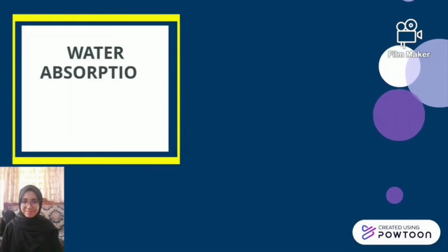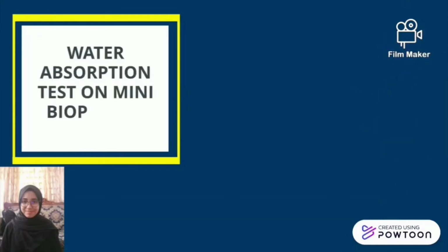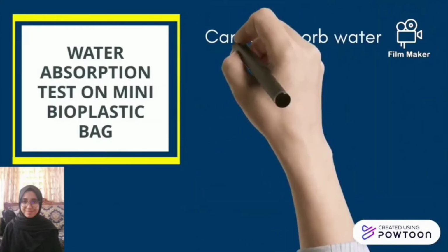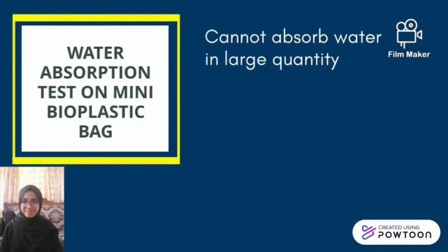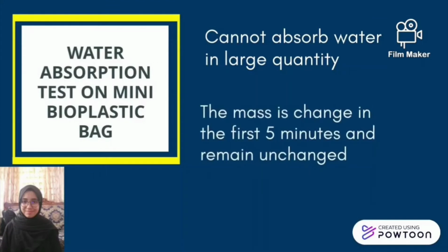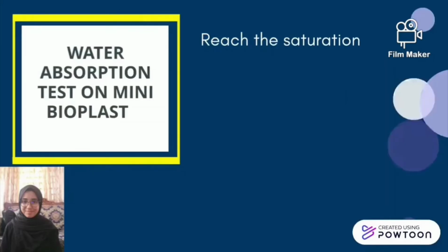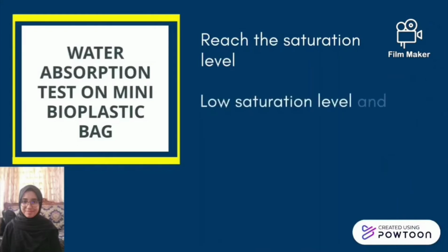Next, I will talk about water absorption test on mini bioplastic bag. From the result, we can see that our bioplastic cannot absorb too much water. The mass of bioplastic after soaking in the water only shows a change in the first 5 minutes and remains unchanged for the next minutes. This means that saturation level is reached. This bioplastic bag has a low saturation level and is not a good water absorber.